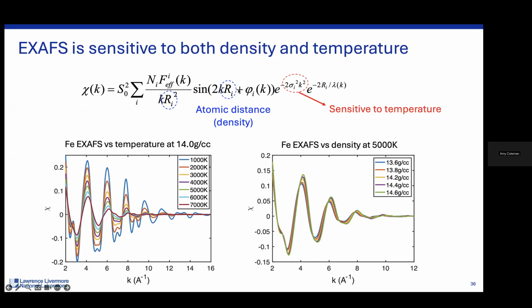This process is sensitive to atomic density - we've got these atomic distance terms in the equation here. We can see this in this simulated XAFS data at the bottom. When moving to higher densities, you can see there is a shift in the XAFS oscillations.